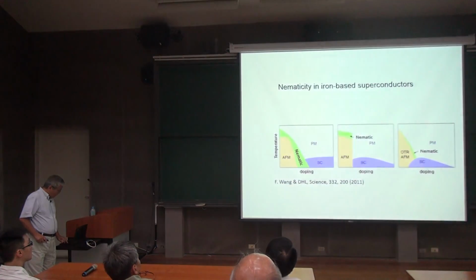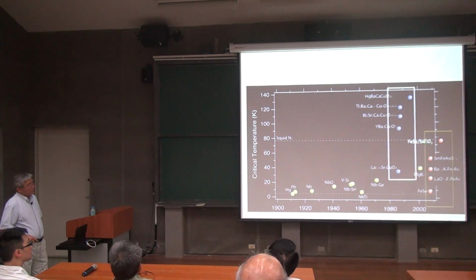Quite recently, in 2006, Hosono discovered a new family of high temperature superconductors, which are known as the iron-based superconductors. And its critical temperature has now been elevated to extremely close to, if not above, the liquid nitrogen temperature. And this highest Tc compound is iron selenide, a single atomic layer of iron selenide deposited on dielectric strontium titanate. By the way, iron selenide was discovered in Taiwan by Maw-Kuen Wu in the bulk crystal form.